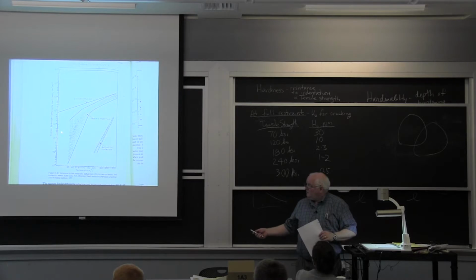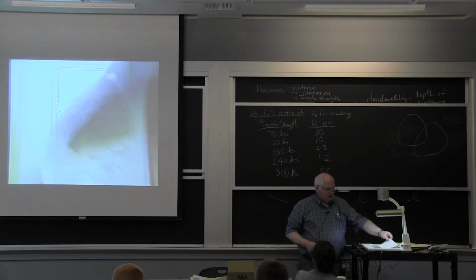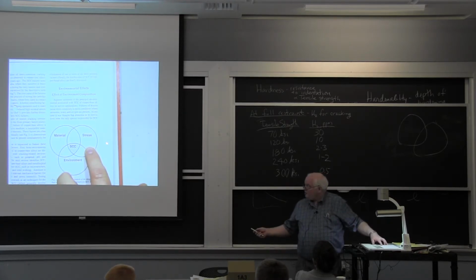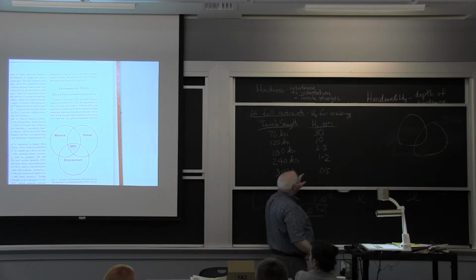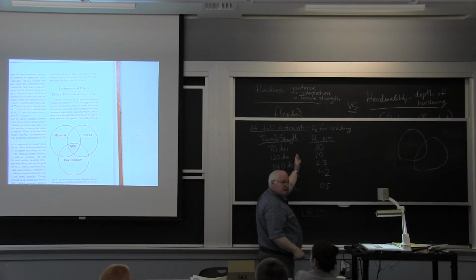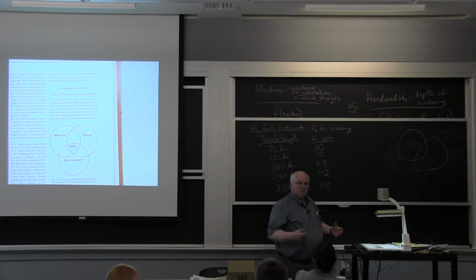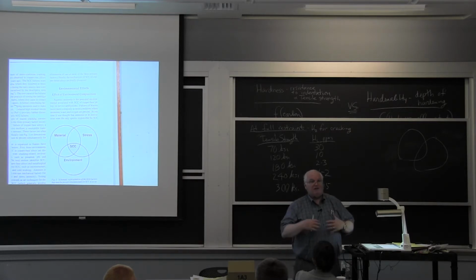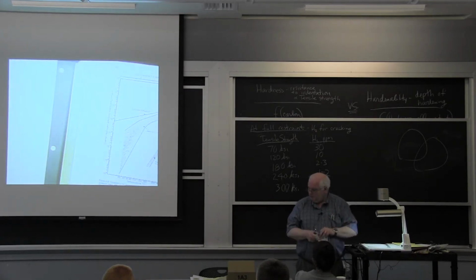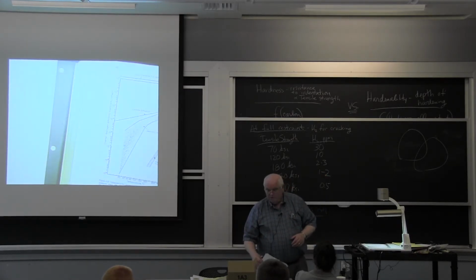This is the kinetics of how fast it might get out of that steel. But I also have to worry about how much residual stress I have, which is what's going to cause this cracking. This environment is sort of Coe's plot of different electrodes and how much hydrogen I put in there. And the material is the strength level of the material, because that tells me how much residual stress is going to be at my maximum if I have a big heavy weldment and I get full restraint. Okay, so all of these things come together, which makes hydrogen cracking very, very complex.